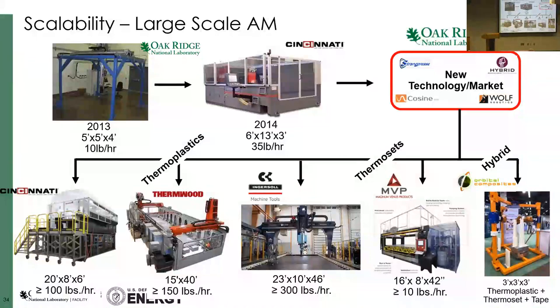So we created a new industry, as you can see from there, when we interlaced everything together, right? We interlaced the process, system scalability, and material scalability, and then you introduce a completely new market, from a blue gantry to 35 pounds per hour, to 100 pounds per hour, and new companies start to get in: 46 foot, 300 pounds per hour, and we are targeting 500 pounds per hour with University of Maine. This system sits at University of Maine. Other new technologies spun off, like thermosets and hybrid manufacturing.